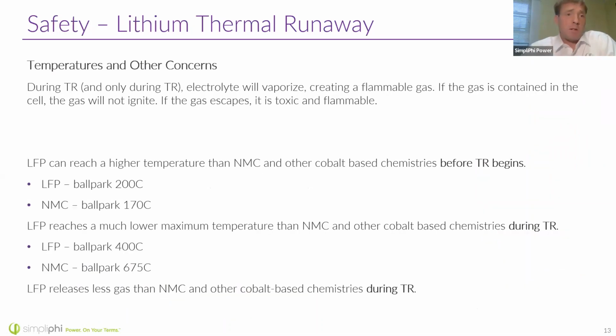Okay, so here's some data about thermal runaways, and this data is talking to you about lithium iron phosphate, about the temperature at which it does go into thermal runaway. These units are in Celsius. If you take a lithium iron phosphate battery and you heat it up to 100 degrees Celsius, which is the boiling point of water, nothing is going to happen. You will have to heat a lithium iron phosphate battery all the way up to around 200 degrees Celsius, which is probably around 400 degrees Fahrenheit. You have to get it very hot, like putting it inside an oven, before you can get it hot enough to go into thermal runaway.